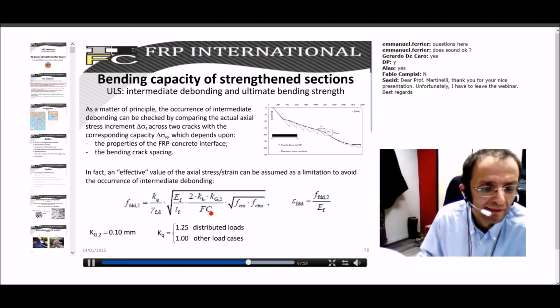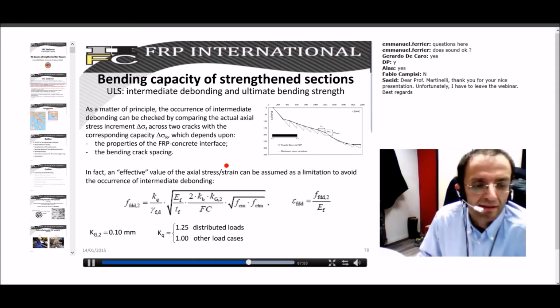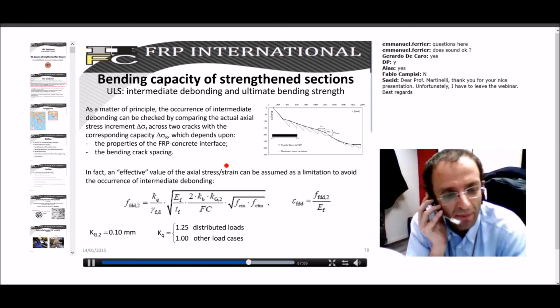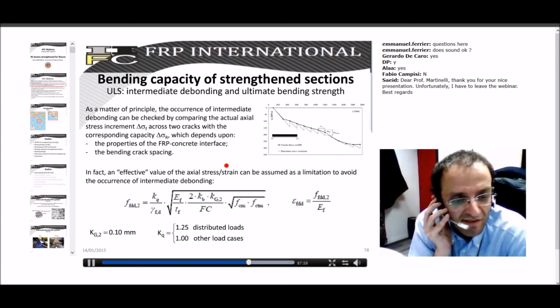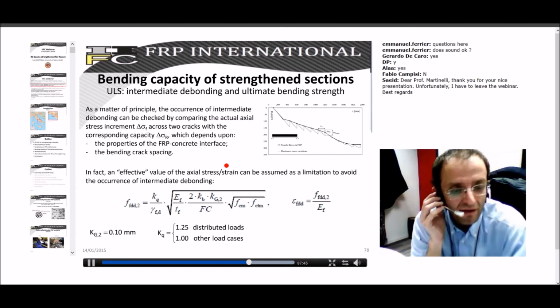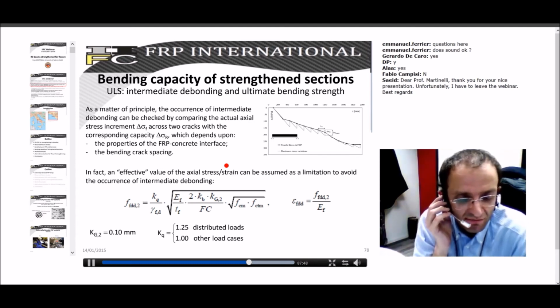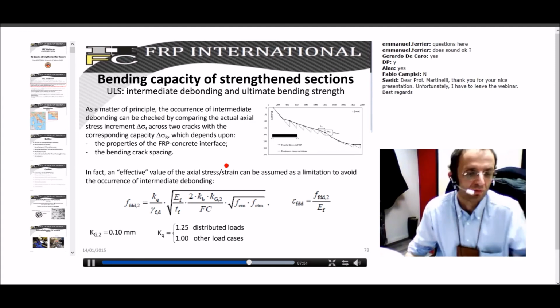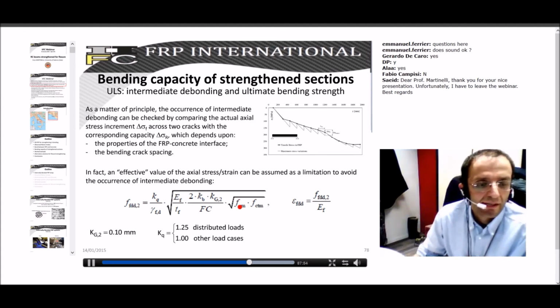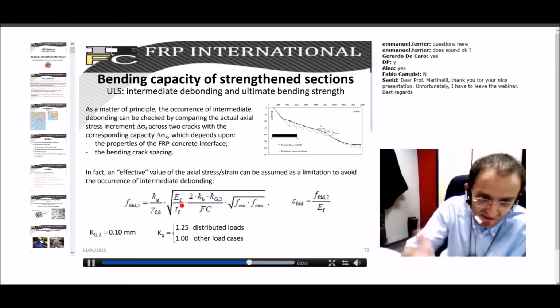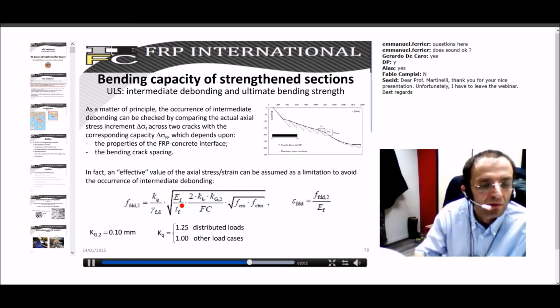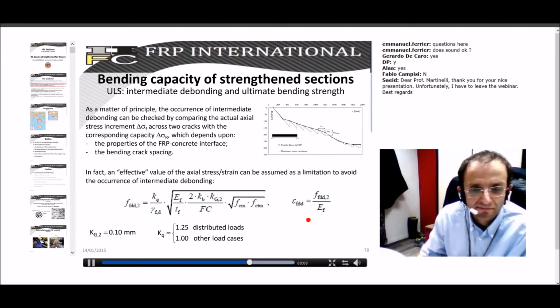FC is the confidence factor, which means since we generally apply this strengthening to existing structures, the FC depends on the knowledge you have of the structure. So on how many non-destructive and destructive tests you have done on your member to evaluate the average compressive and tensile strength. So FC can be either 1.2 or 1.35, in the Italian guideline, depending on whether you implemented a more accurate or less invasive testing campaign.